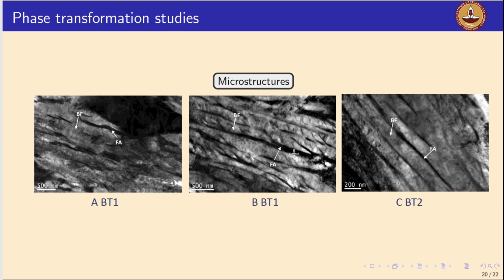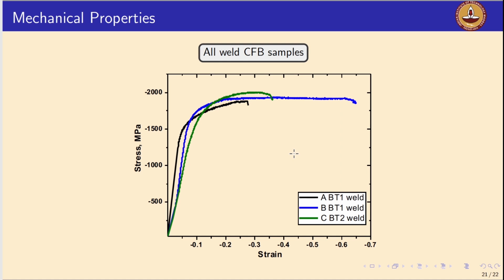And subsequently, once we identify these isothermal bainitic holding temperatures and time, we can make the welds and study the mechanical properties again using Gleeble. So we take the weld samples, we use Gleeble compressive tests to identify the mechanical properties. If you look at the three optimized weld thermal cycles, they produce excellent mechanical properties.